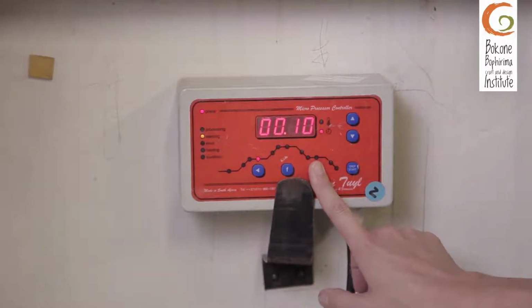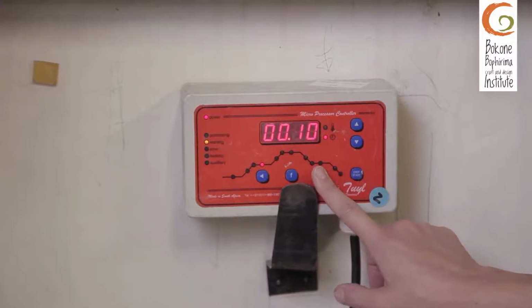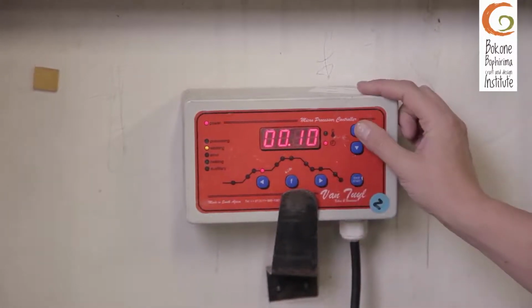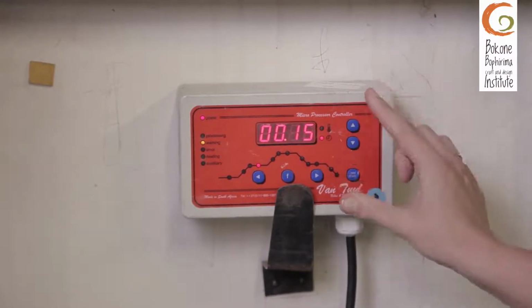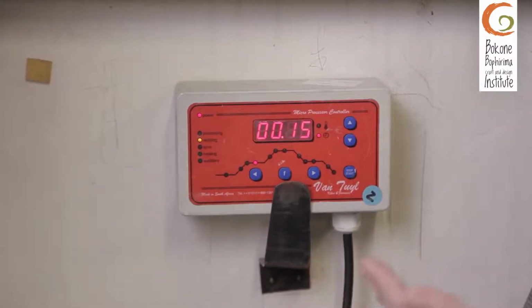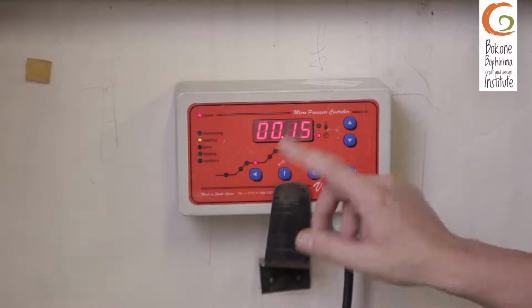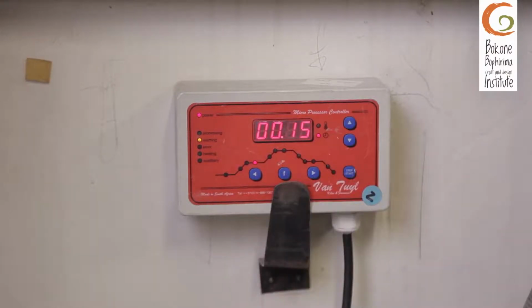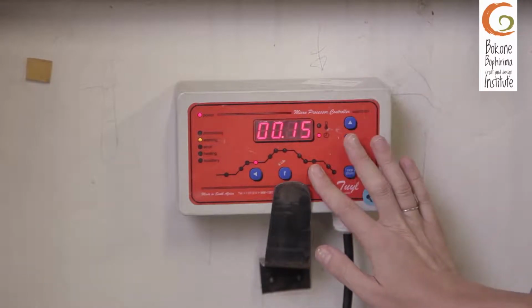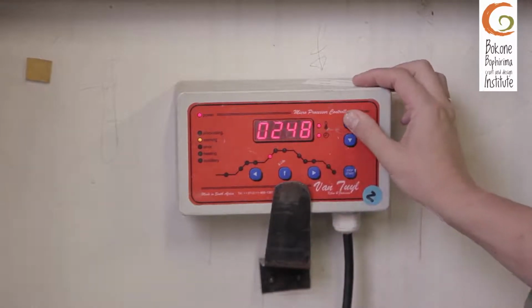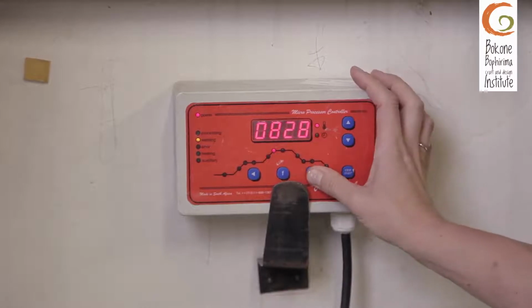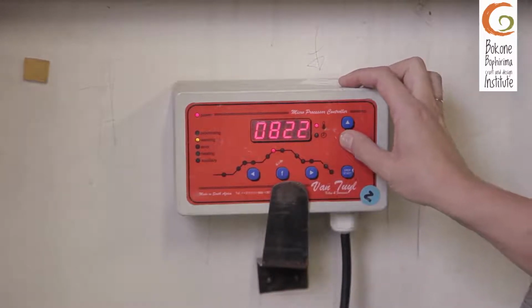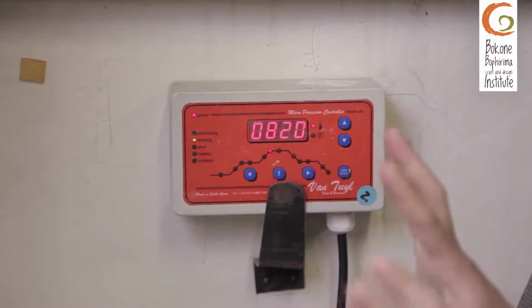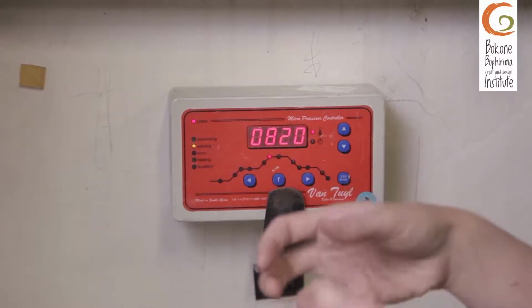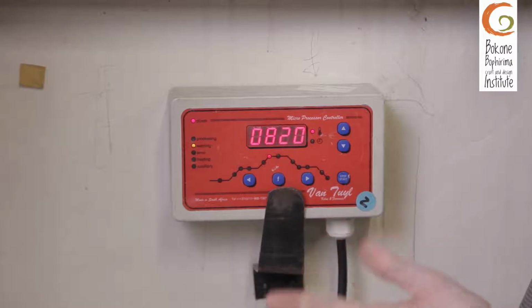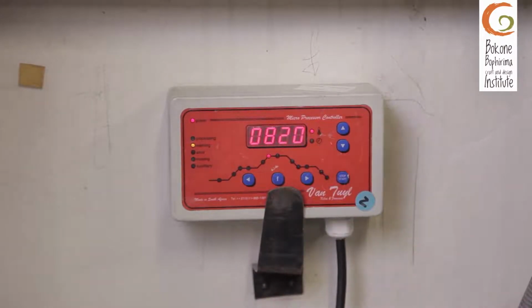I am then going to hold that temperature for 10 minutes. Actually, no, I'm going to hold it for 15 minutes. Reason being, I've got two layers of glass and I want to ensure that my bottom painted layer is also at 580 before taking it up to its top temperature. I'm then going to take the glass up 250 degrees an hour up to my top temperature of 820 degrees. And at 820 degrees, my glass will become soft and the edges will fuse to become one on the surface. So it will not be seen as two layers of glass anymore.